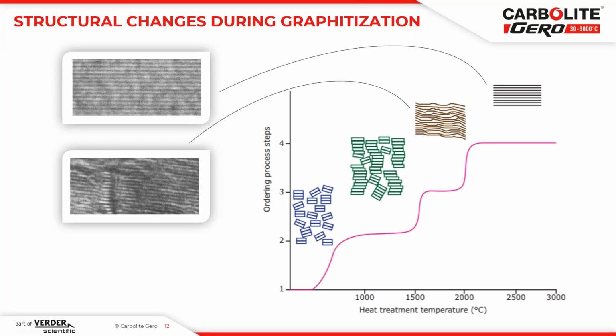As you can see in the diagram, we have multiple steps from the raw material to the final graphitized carbon material. At the very beginning, we start with a highly disordered arrangement. It becomes step by step more and more ordered up to 2000 degrees, which is about the carbonization temperature. There are still some defects and some three-dimensional arrangements available. Then up to 3000, mainly between 2800 and 3000 degrees, the graphitization takes place. This is very important to ensure the distances between the graphite layers so that the ions can move freely. Next slide, please.